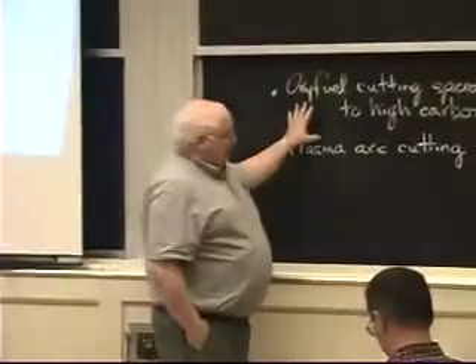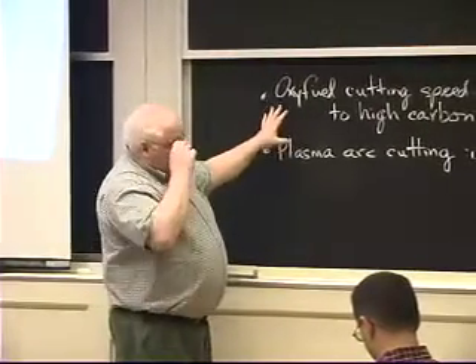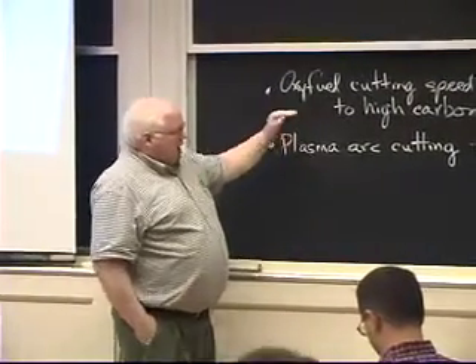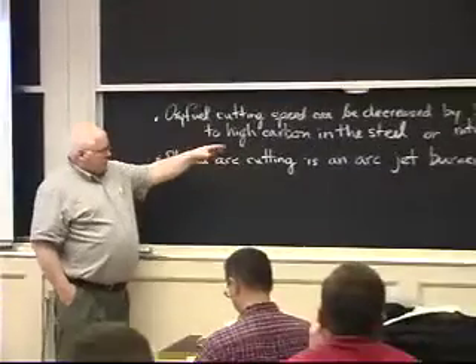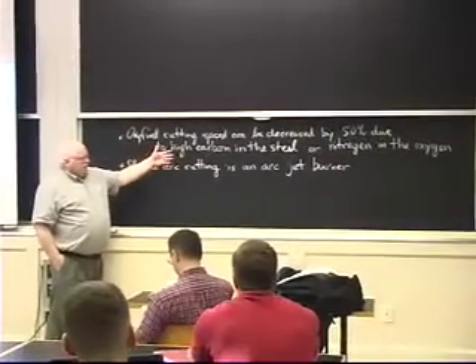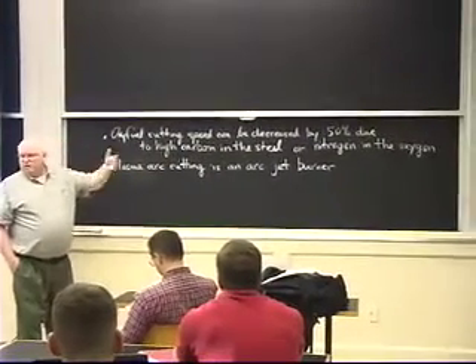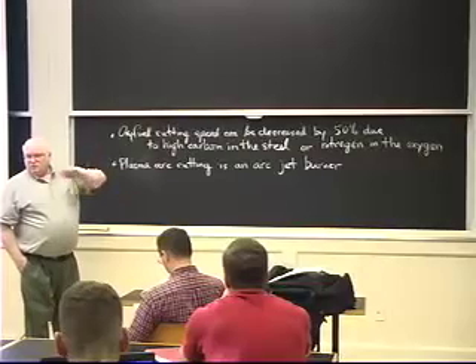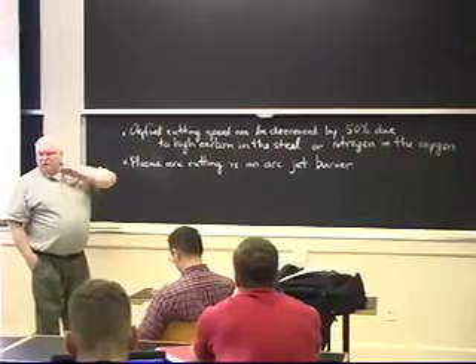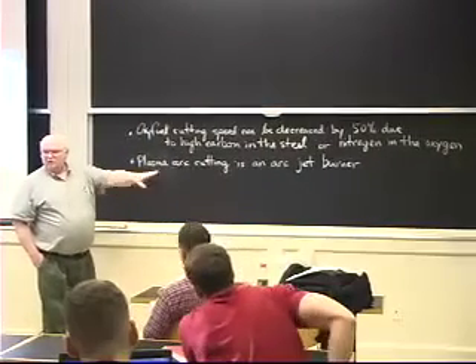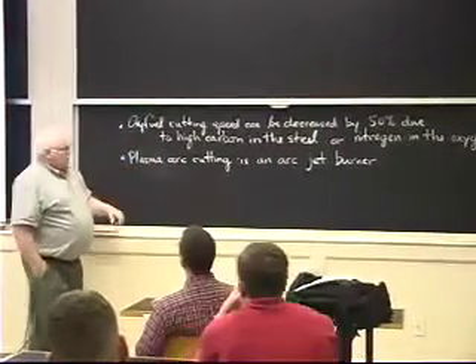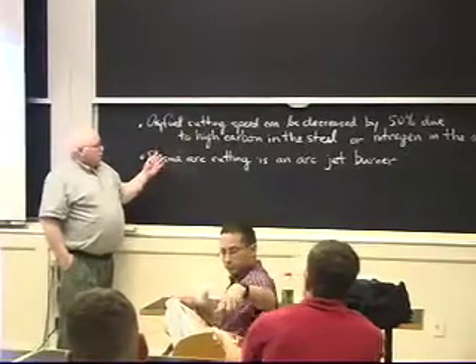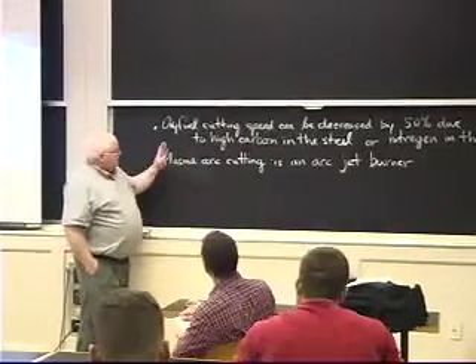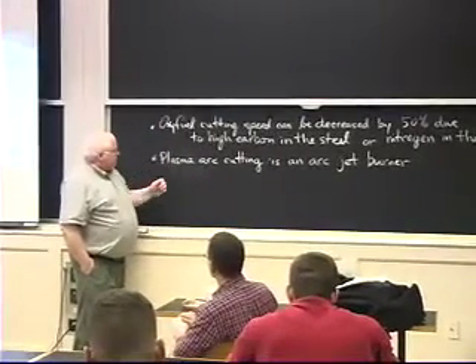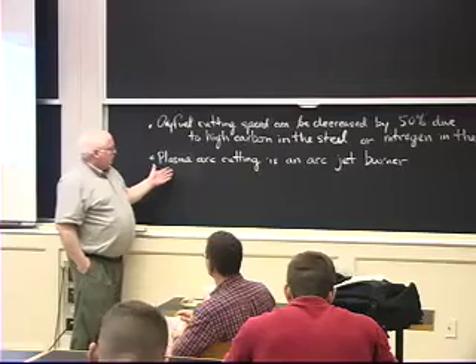Those are replaceable tips. We talked about oxy-fuel cutting last time. The speed can be decreased by 50% due to the high carbon in the steel, which generates carbon monoxide or nitrogen in the oxygen, and both of those create a boundary layer, whereas ordinarily the oxygen would just be consumed, there'd be no boundary layer, and you'd have excellent heat transfer, get nearly 100% of heat transferred to the surface to cut, rather than 2% that you would get from an oxyacetylene flame, where you have a big boundary layer with lots of leftover carbon monoxide and water vapor and stuff.